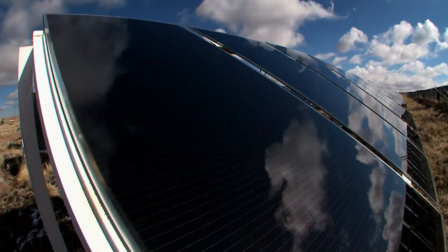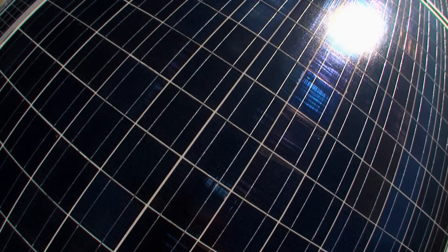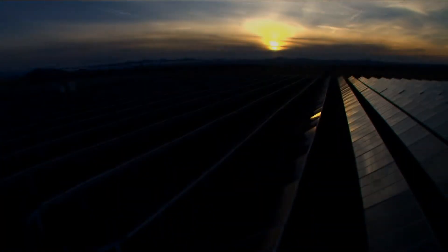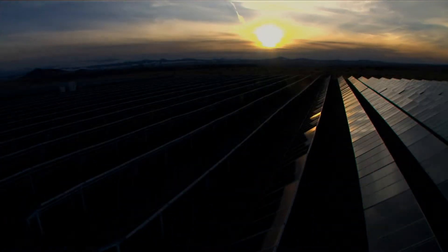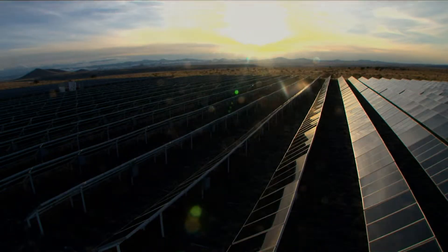Most solar cells have to have some kind of crystallinity, which means inevitably they're slow to make and cost a lot of money. If we can break that reliance on highly structured, well-organised materials and move to an excitonic material — where the energy is localised so it doesn't interact with defects — then it becomes compatible with spray coating, solution coating, and float glass manufacturing. Those kinds of technologies can really have a big impact on our energy problems.